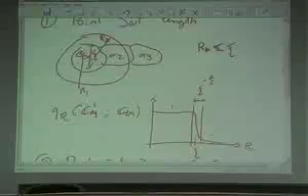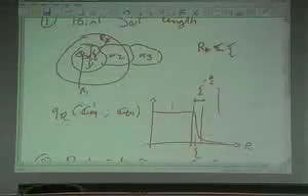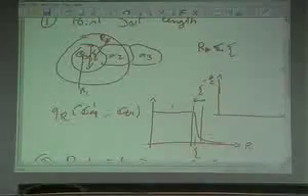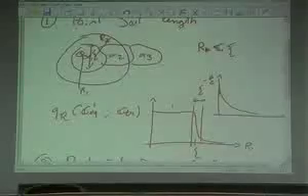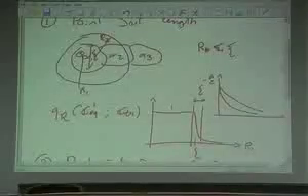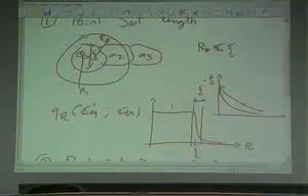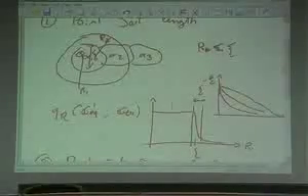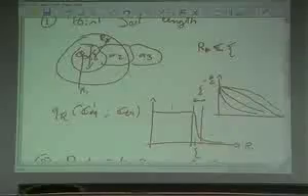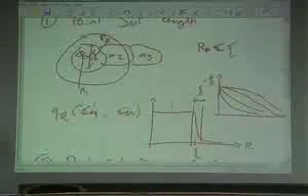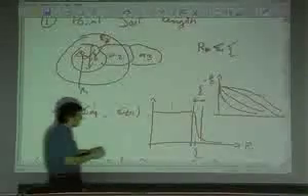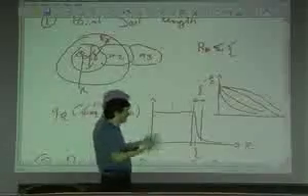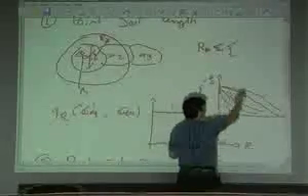But the really important thing is that what you get in simulation is not a sharp crossover. At high temperature it goes down this way, and then as you decrease the temperature it goes this way, maybe I'm exaggerating a little bit. Then you decrease the temperature, and it looks like it becomes a little bit more sharp, but it's still very smooth. So the important thing is that clearly there is a length which is growing. You forget the boundary condition on a length which is larger and larger, the lower the temperature. But this is clearly smooth.